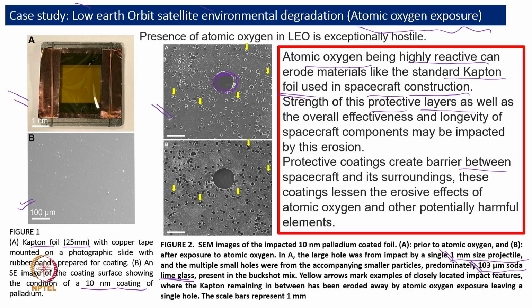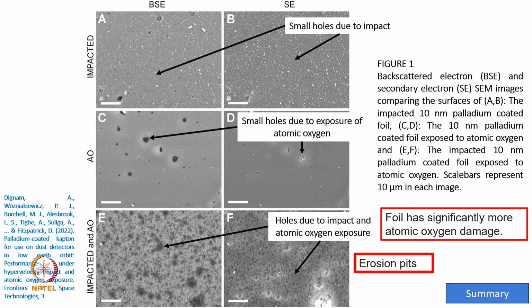So A shows without oxygen, and B shows in presence of oxygen. When they exposed this surface, they found that the size of the impingement, maybe the hole size, is increasing in presence of oxygen. So this has been shown, and then they performed more experiments to get better results.